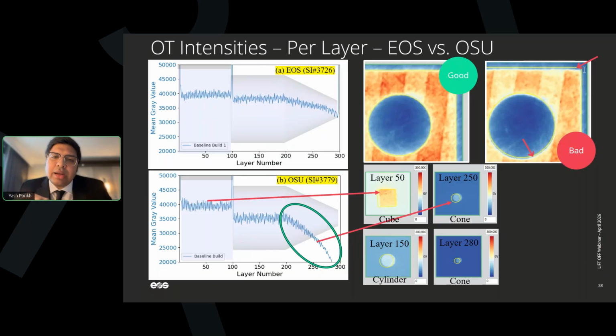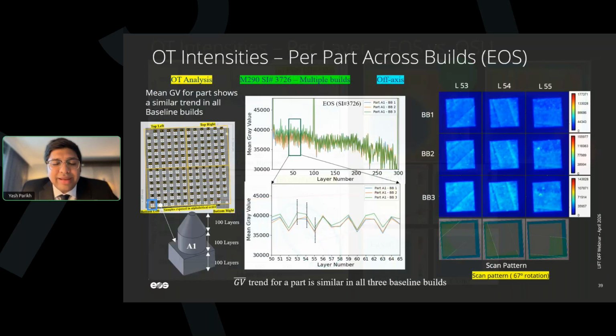So it was dropping down on this behavior. You see the layers which are good in case of our machine, the signature is fine, but as you can see for layer 250, a sudden drop happened around 280 onwards, and that has to do with the misalignment. But you can get it fixed as well. But this was how we got to identify the problem as well. Go to the next one. As I told you, I have like 30 more slides, so we need to hurry up as well.